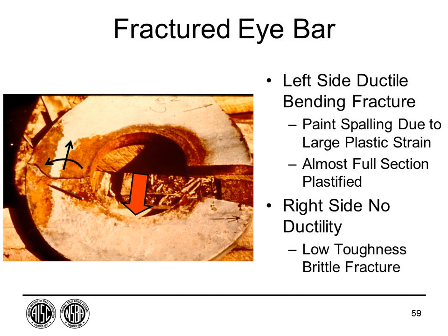So the important thing about this, when you look at it, is to understand that this material on the left-hand side behaves like a tensile specimen. It had good ductility, looks really good. It's not a sterling material. Its tensile properties would be similar to a rebar or something like that, but 10 to 14% elongation, not too bad. This side over here, we have no ductility, and this is the same material on both sides. So the lesson that we learned was, well, what happened on that other side? This was the new thing.